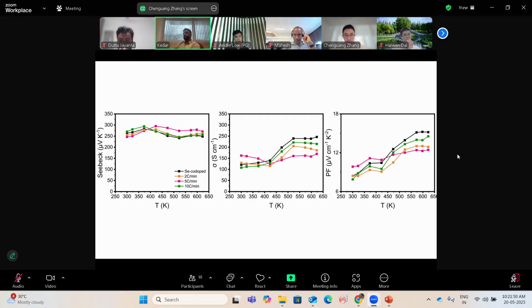Now, the problem with all of this is that the selenium co-doping has to be done initially. So now you have this issue where not only is the cadmium diffusing everywhere, so is the selenium. And that could cause a problem because your vacancies go. So it's going to be an issue, right? When you do co-doped samples and post-annealing, there's no way to introduce selenium later. That's one of the problems over here. I don't know how to circumvent that issue.